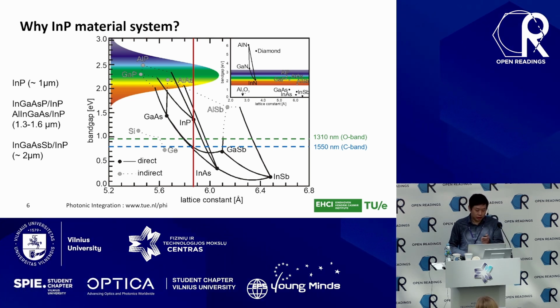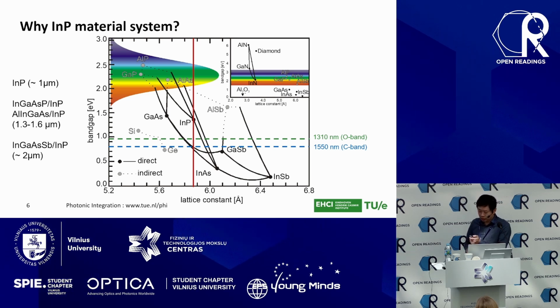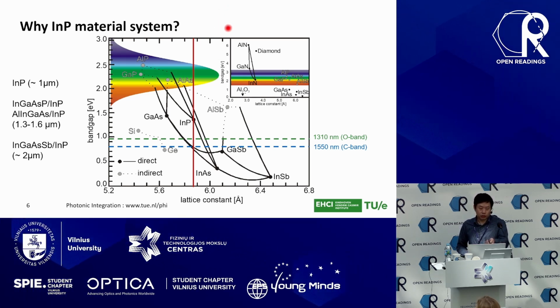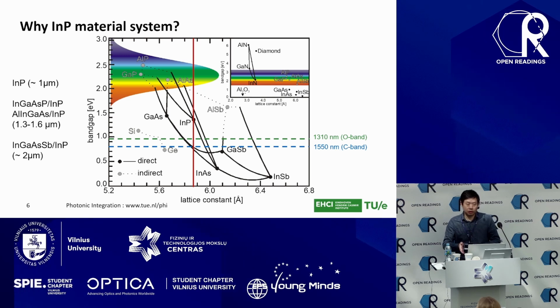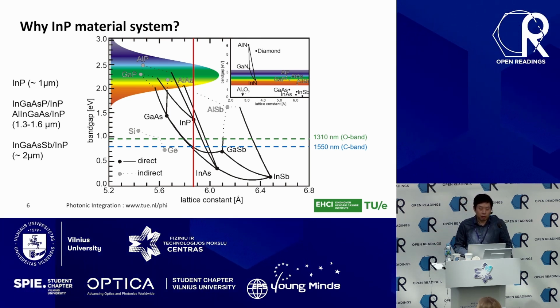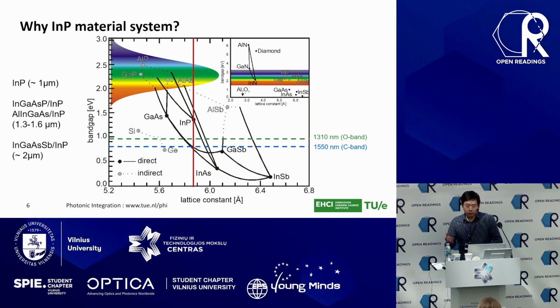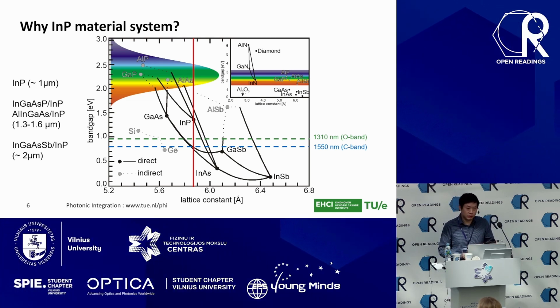because, as you can see in this diagram of lattice constants versus the band gap, I draw a straight line from indium phosphide down to the cross section between gallium arsenide and indium arsenide, this line. At this intersection, we have a ternary compound, indium gallium arsenide, which has a lower band gap but the same lattice constant, so we can achieve lattice matching. And then the more interesting thing is the red line between indium phosphide and indium gallium arsenide, because on this straight line, you can have the quaternary material, indium gallium arsenide phosphide, where you can always maintain the lattice matching while having a flexible bandgap tunability. And it covers both the O band and the C band wavelengths. So that's why indium phosphide has become so interesting, originating from optical communications.